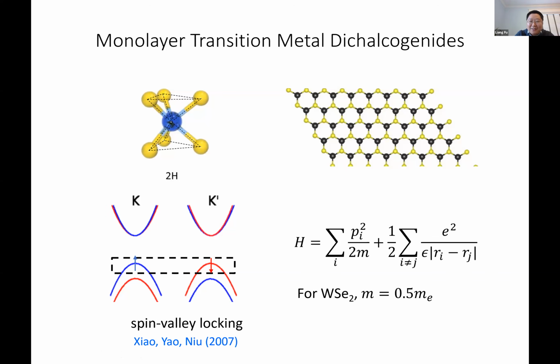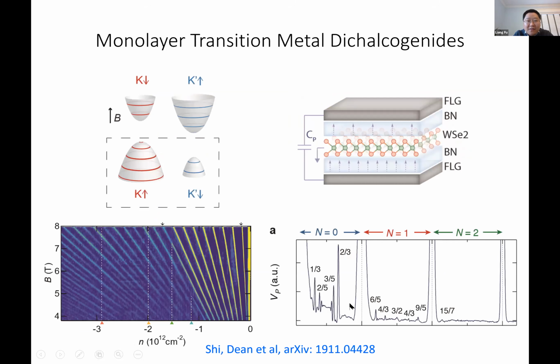So this is perhaps the simplest realization of the uniform electron gas in 2 dimensions. In this case, it's a uniform hole gas. And the effective mass is about half of the electron mass for this material, tungsten diselenide. And just to show the rapid progress that has been made in improving the material quality, this is a very recent work from the Columbia group.